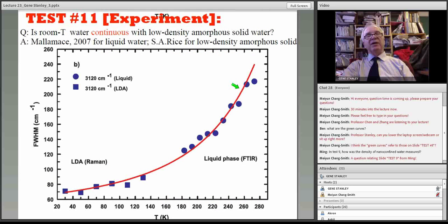We could skip this if you want, but we've been saying that the liquid is continuous with the low density amorphous solid. And that's what this curve shows. It's merely the data for the full width at half maximum of the experiments that we've been looking at, the FTIR experiments, and this is the decrease down to the lowest temperature you get even in confined water. And then these are experiments that the Stuart Rice group made long time ago of low density amorphous solid. And you see there's a region where there are no data, but it's at least plausible that these data are continuous with these data, further supporting the idea that low density amorphous solid water is nothing other than the extension of ordinary water to low temperatures.